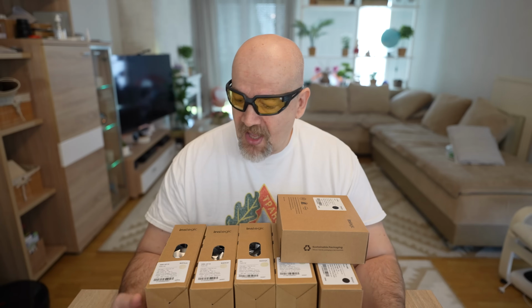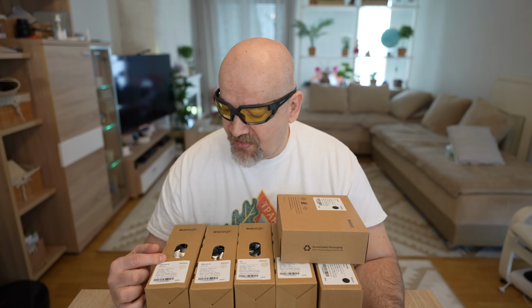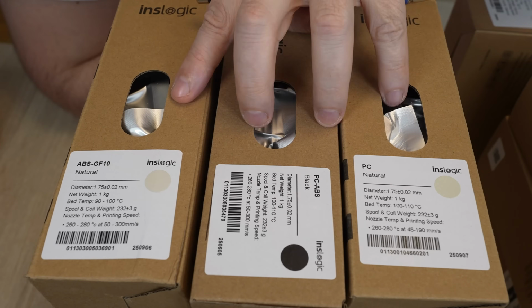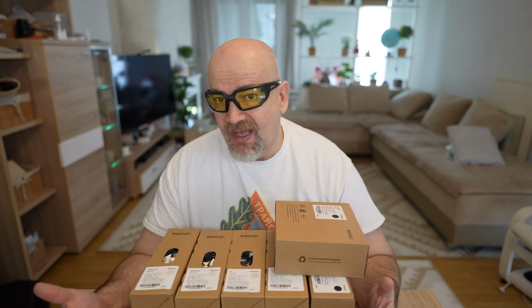About ABS, it is much tougher compared to PLA or PETG, but this one is reinforced with glass fibers. 10 is probably the percentage of the fibers in the filament, and this will make the material more brittle. But why I like these fibers in ABS or ASA is that they reduce the shrinking. This means easier printing and better dimensional accuracy. But how does it affect the other properties? Well, we will see in this video. And another important property of these three filament types compared to PLA or PETG, they have much higher temperature resistance, which will also be tested in this video.